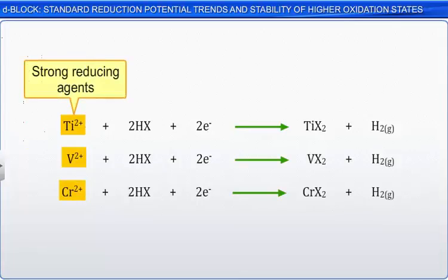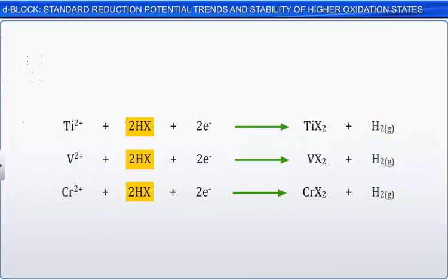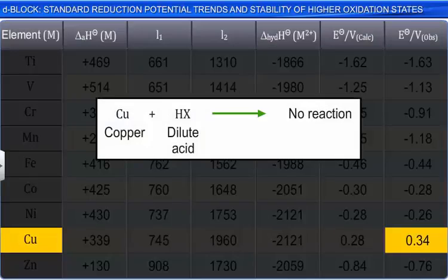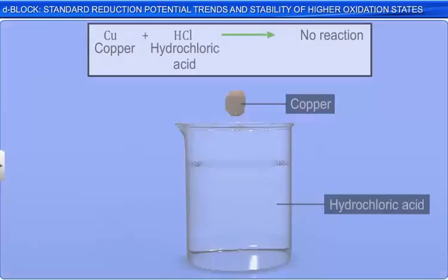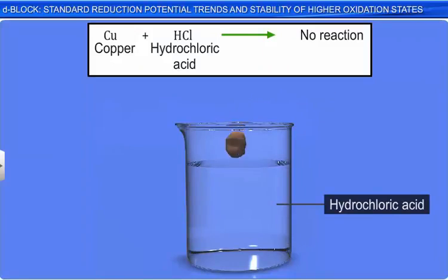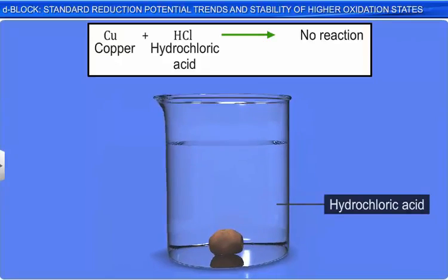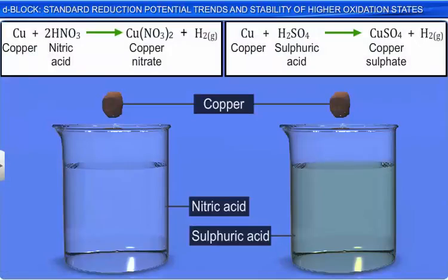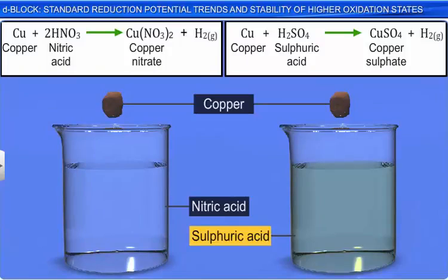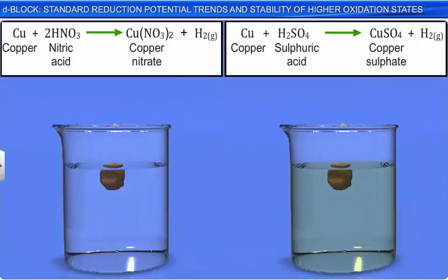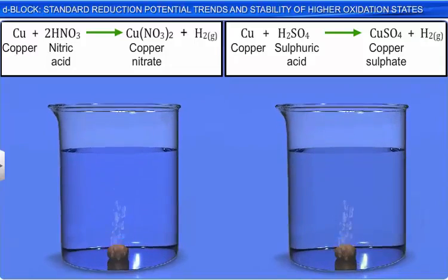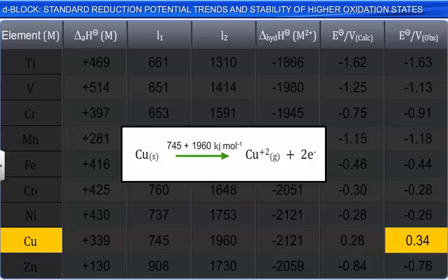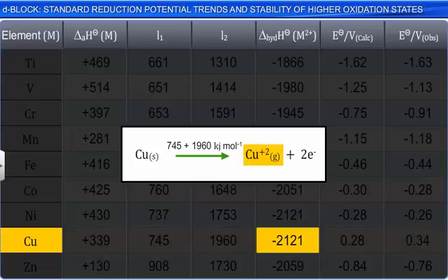On the other hand, copper, with a positive reduction potential, does not liberate hydrogen from dilute acids. Thus, copper is inert towards non-oxidizing acids such as HCl, but reacts with oxidizing acids such as nitric acid and hot concentrated sulfuric acid, as shown here. The reason for this behavior is the high energy needed to transform solid copper to gaseous cupric ion, which is not exceeded by the hydration enthalpy of the ion.